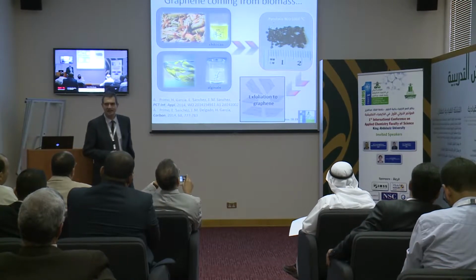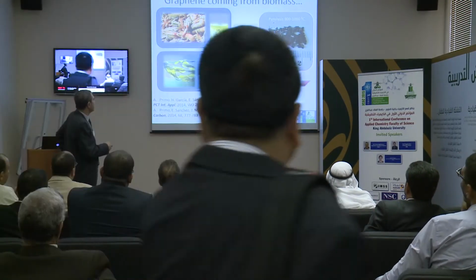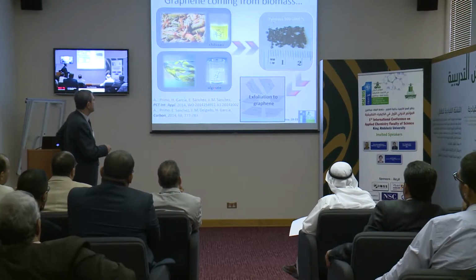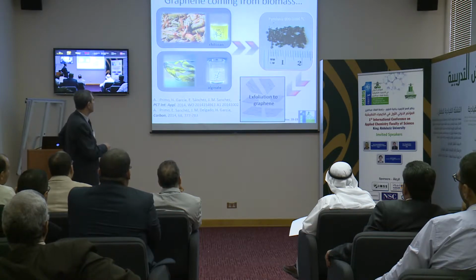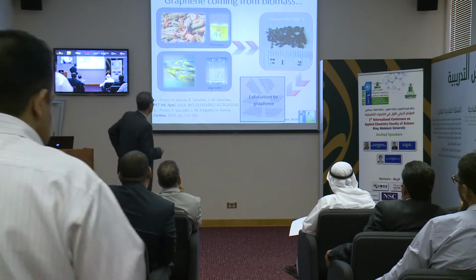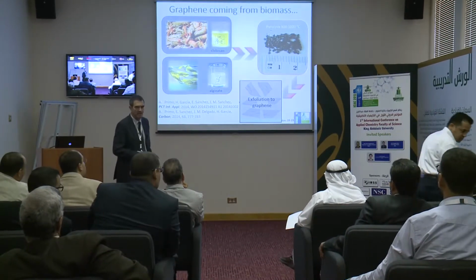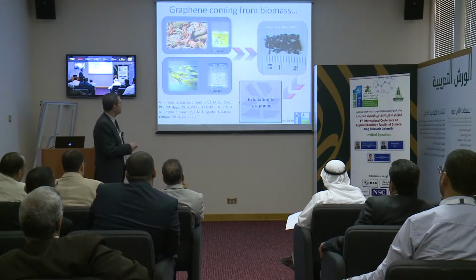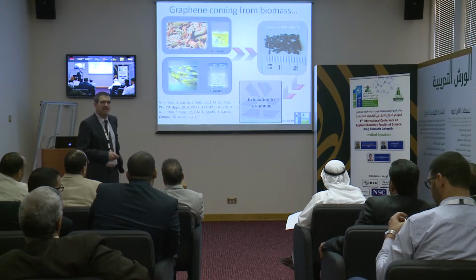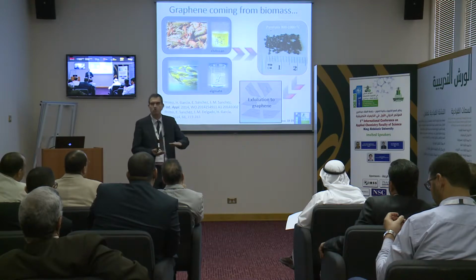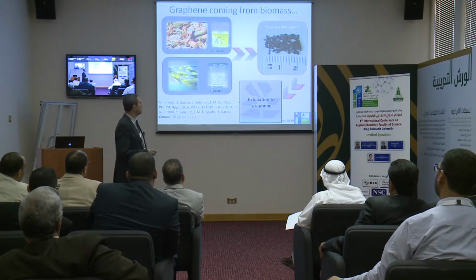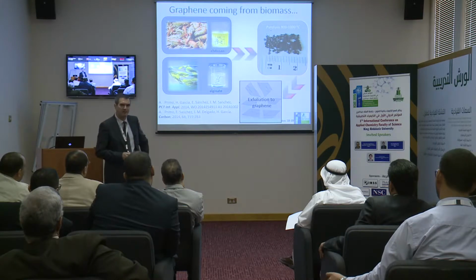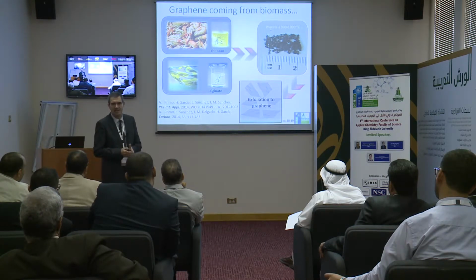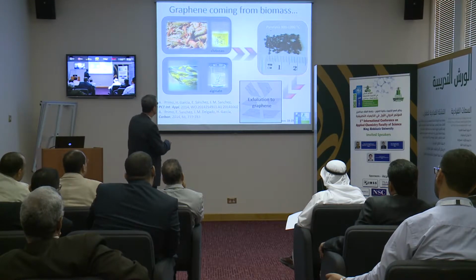So let me show how we prepare graphene. We start with some biopolymers. Typically they are polysaccharides, for instance alginate or chitosan, and they come from biomass. So here it represents the origin of these biopolymers. They are renewable materials, and then what we do is we pyrolyze these biopolymers, and then we obtain some carbon. This was already known a long time ago. This carbon is called turbostratic, stratus being layer in Greek, and turbo means that the layers are not well packed. And also these carbons are called graphitic because they tend to be like graphite, but it's not really still graphite. So we pyrolyze these precursors, these polysaccharides.